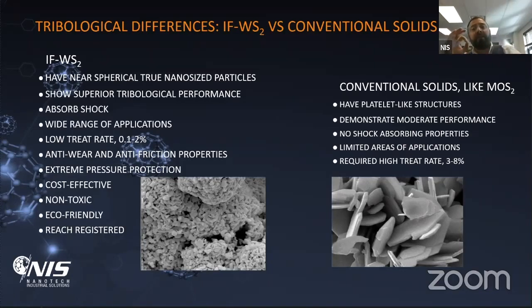Because of the spherical nature and hollow core, under shock and impact, this particle absorbs it, and they have very good elasticity. Unlike many other solids, which have a regular crystal structure and don't have a hollow core, they transfer the shock to the metal surface, creating micro pitting and micro cracks. It was shown many times in the past, probably 12 years, that tungsten disulfide spherical particles absorb the shock and dramatically reduce micro pitting and micro cracking, having this unique morphology with the hollow core.